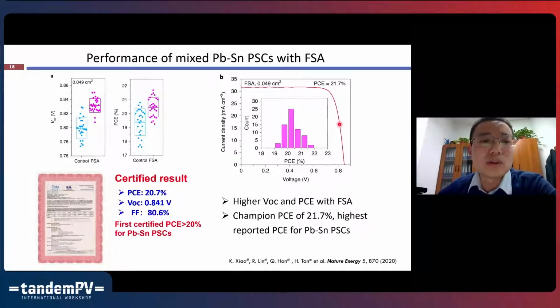And we also made smaller area single junction narrow bandgap perovskite solar cells, and we also see that with these additives we can much improve the open circuit voltage and also the efficiency of the devices. The best efficiency we can get in the lab for the small area devices is 21.7%. We also sent one device to Newport for certification, and it gave us an efficiency of 20.7%, with a reasonably high open circuit voltage and a high fill factor value. This is the first certified value higher than 20% for tin containing perovskite solar cells.